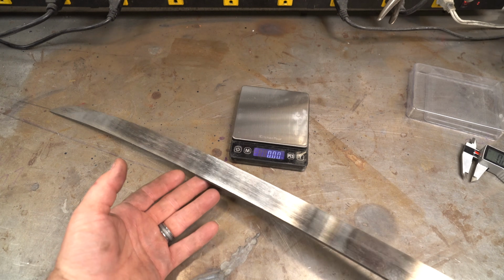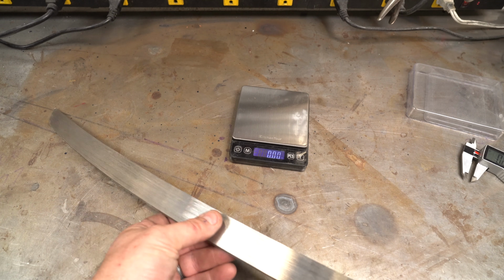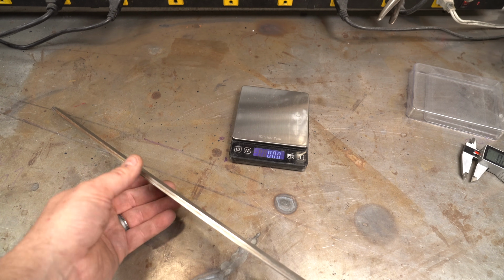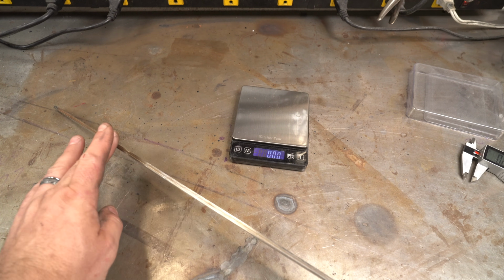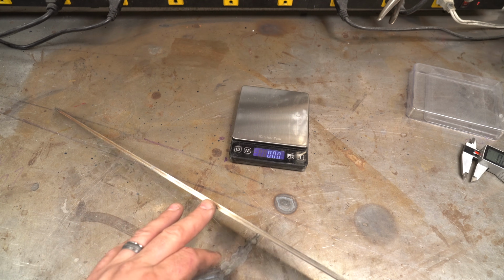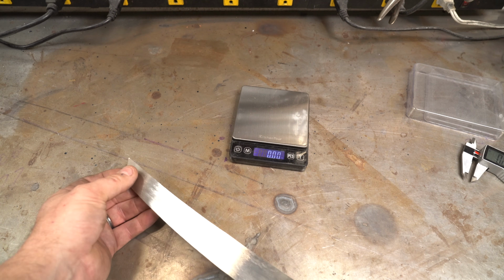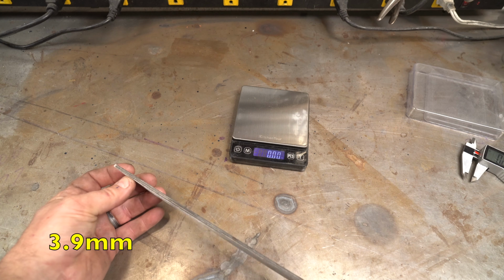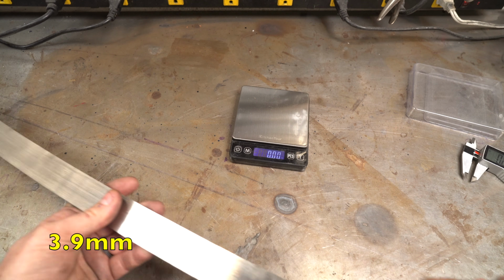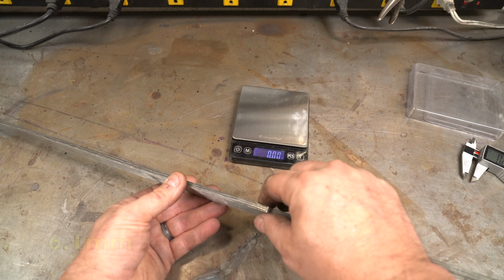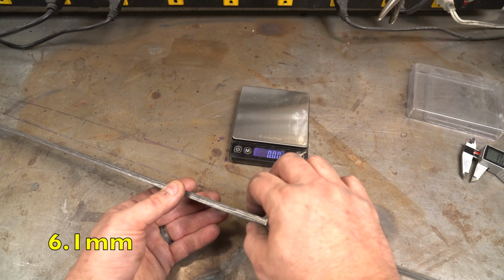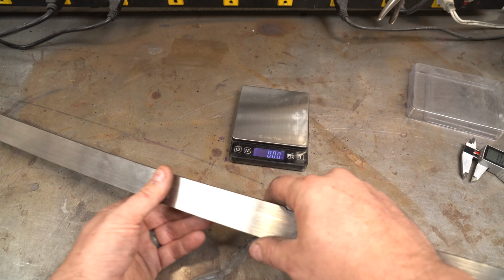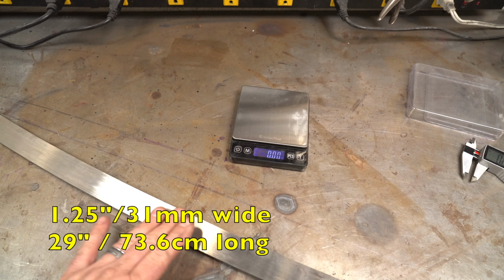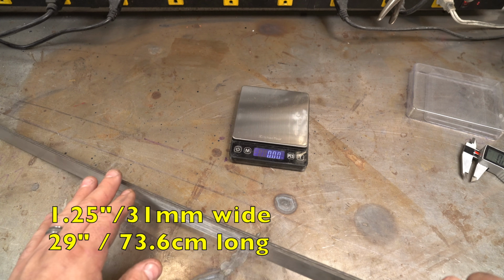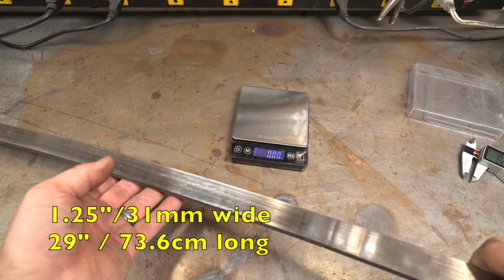Okay, after a couple hours of grinding, we've got the blade all nice and tapered. It takes a while to get the taper right on this and maintain the core. It's about 154 thousandths, or 0.154, at the tip and just under a quarter inch, so 0.24, right here, which is great. That's exactly what we want. I still got a lot of grinding to do, so that'll come down after final grinding anyway.